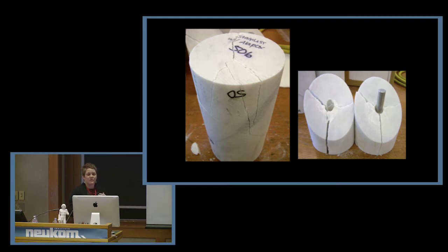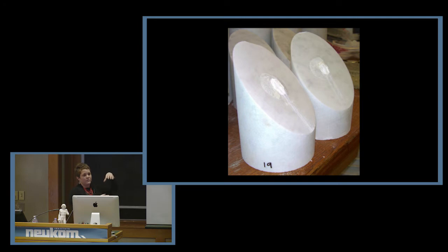But we have to think about a lot of different scenarios. What if the sculpture falls down again? If there were a big stainless steel pin inside that sculpture, it would fracture in a similar way to this. It would just kind of explode around the stiff pin. So we wanted something that was more compatible with the marble, and that turned out to be fiberglass. What you see here is a core that was assembled with a fiberglass pin. It was pushed to failure, and the thing that failed in this case was the fiberglass rod and not the marble. So this we really liked.